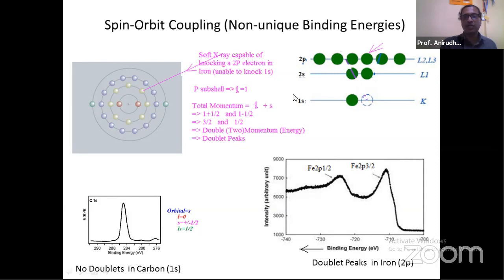And so a few of those electrons which are ejected from 2p will have an energy corresponding to this 3 by 2. And a few electrons which are ejected from that same orbital can have a value corresponding to 1 by 2. Because they possess two different values for their momentum, their energies can also be different, and therefore you will see two different peaks which are close by, one corresponding to the 1 by 2 value and the other corresponding to the 3 by 2 value. They are designated as Fe 2p, meaning iron, 2p orbital, but corresponding to minus half spin, so that is Fe 2p 1/2. And the other one is again Fe 2p, corresponding to a spin of plus half, which is giving an L plus S value of 3 by 2, whereas the first is giving a value of 1 by 2.